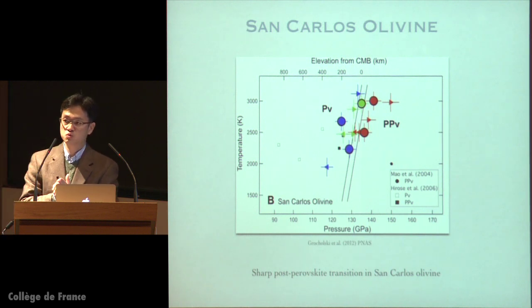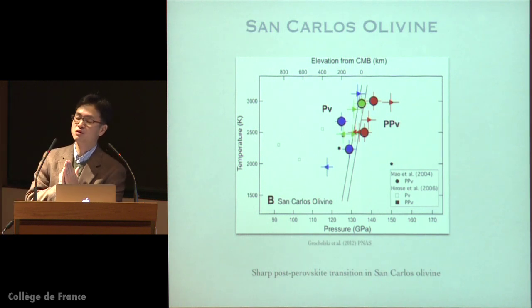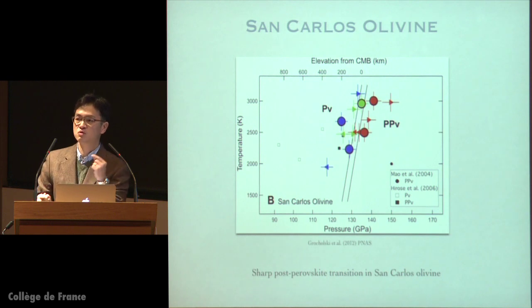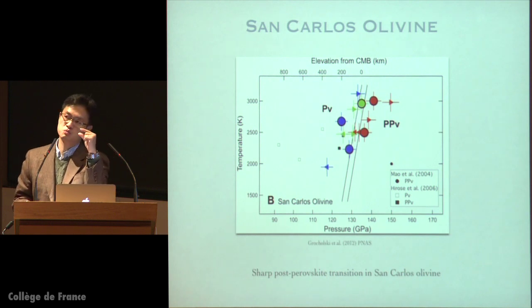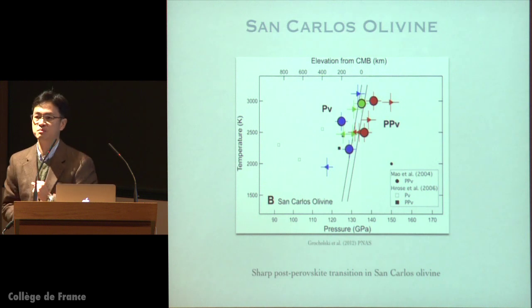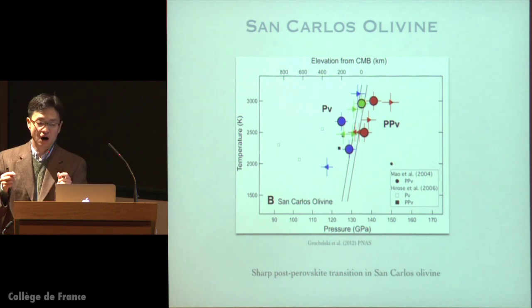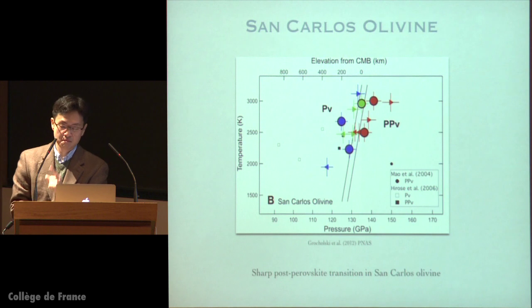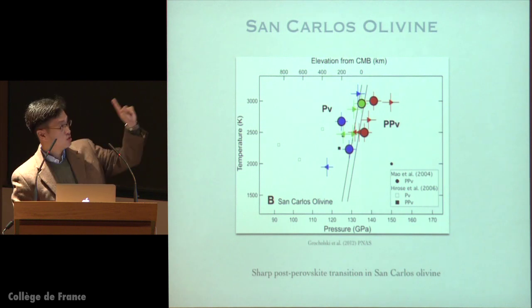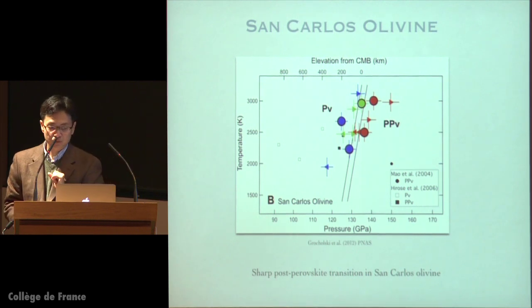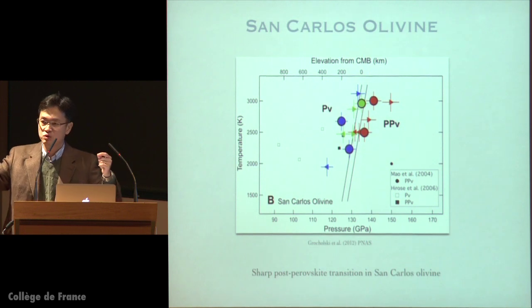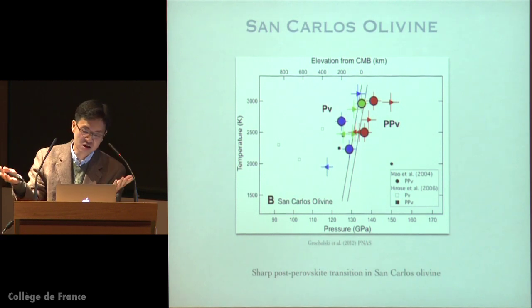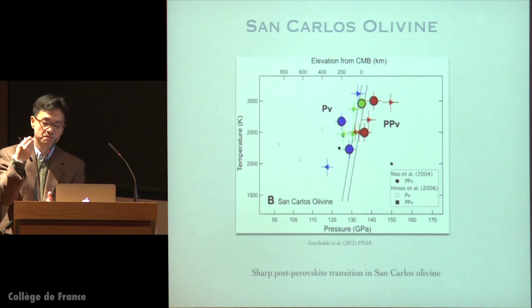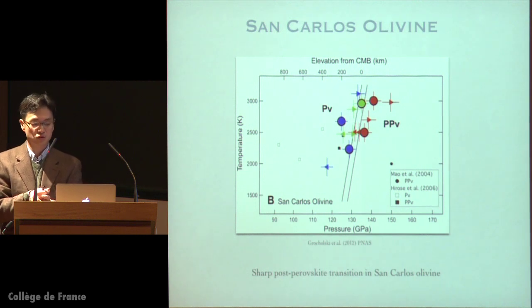You can see two different symbols here, triangles and circles. Triangles were the measurements we performed using so-called reversal measurement. What that means is that we synthesize perovskite or post-perovskite and change the pressure, and see what happens. That's method 2 that we use. Method 1, which is shown by the circles, just brings up the fresh samples and heats them up and sees what happens. So that's a conventional method that was performed by other experimental groups.